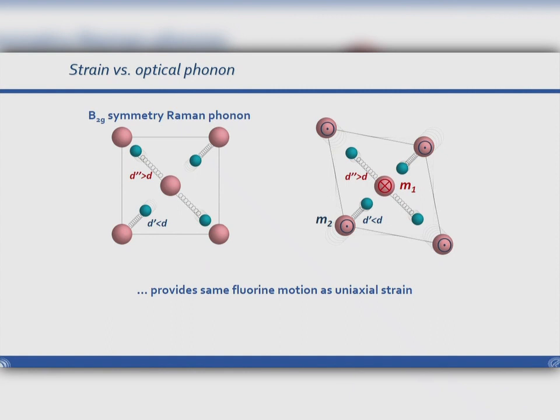So what you have to do is change the distance between the cobalt and the fluoride atoms, right? When you do this with strain, at the same time, you change the size of the unit cell. Therefore, you cannot do this to infinite amounts because, at some point, the crystal will break because of too much strain. However, and this was explored by Paolo Radaelli when he was visiting us, there is a certain optical phonon, a B2g symmetry Raman mode that breaks the symmetry of this compound, which actually has the same distortions, the same changes in bond length between cobalt and fluoride, and this in principle should lead to the same net magnetization induced in this material.